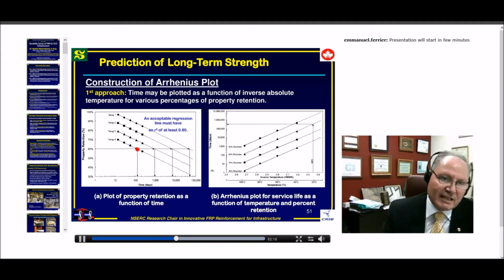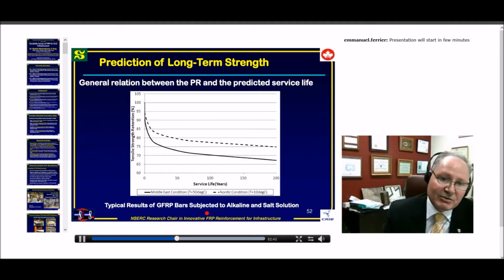And if we look here, all the curves are really parallel. So it means we had only one degradation mechanism, to which the Arrhenius will apply. Otherwise, if they are not parallel, it means we have some combined two or three degradation mechanisms and we cannot use Arrhenius. So you have to be really very careful when you are doing this testing, and this should be all parallel as shown here.